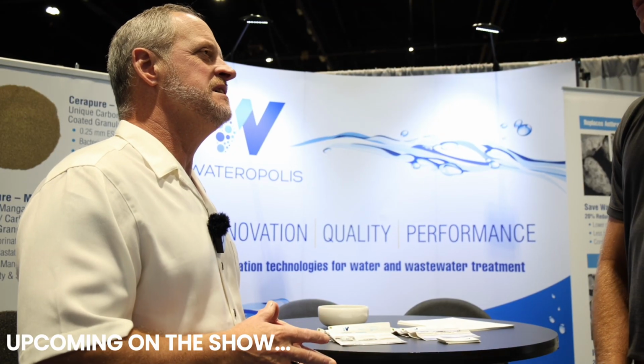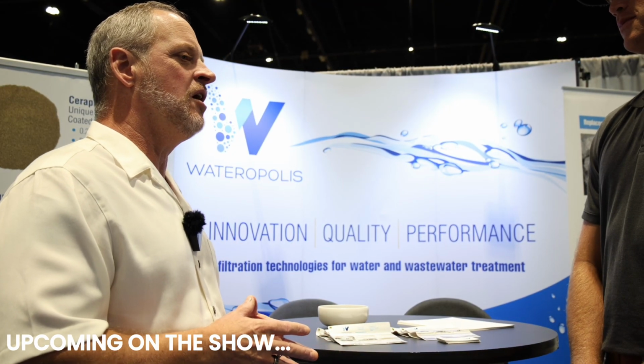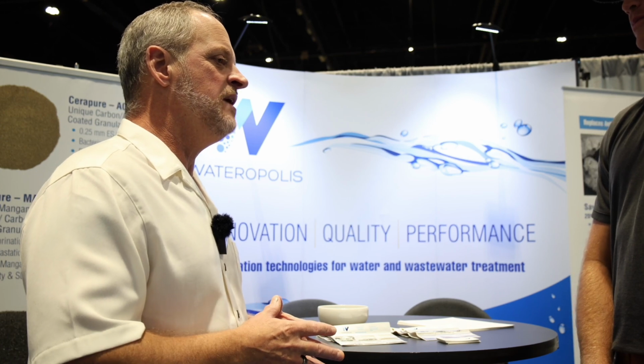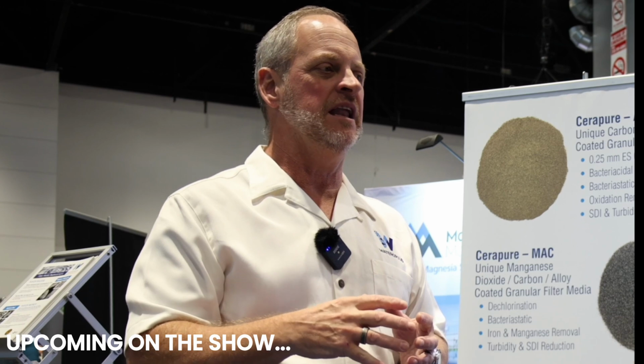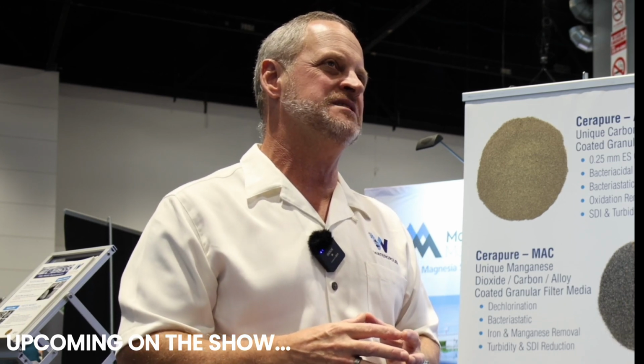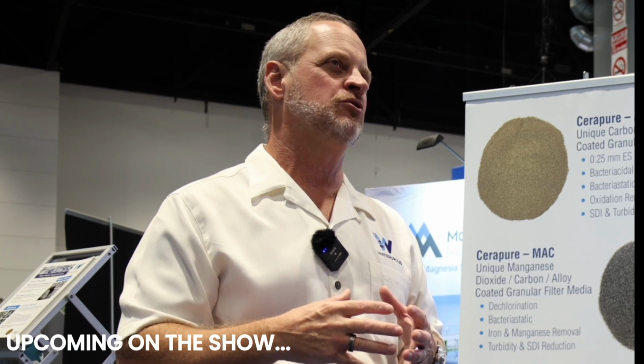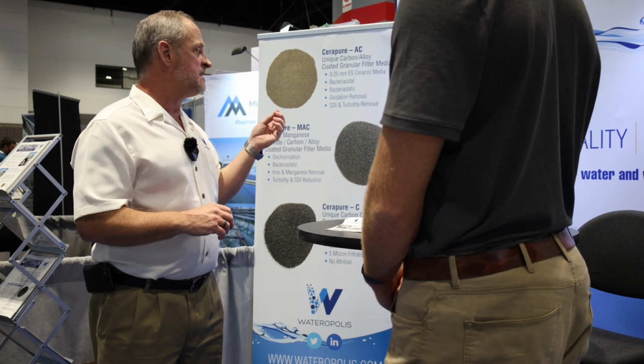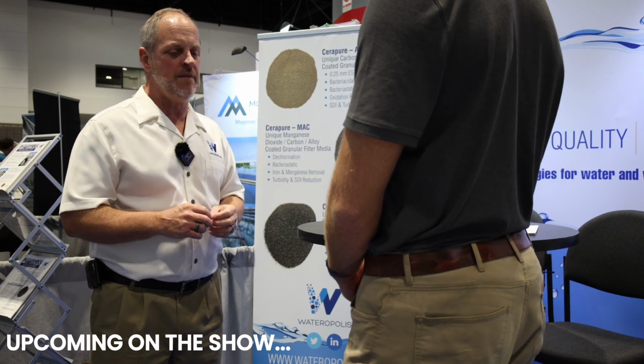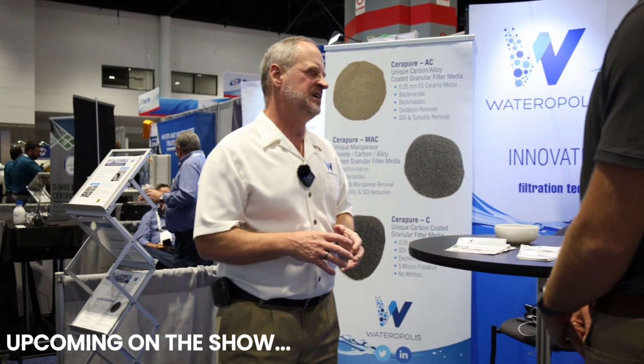Iron is generally easier to remove. You know, you can oxidize iron and then you have a number of choices. Most removals are a little less fussy about which crystal structure it ends up being. I guess the point is that manganese is a complicated mineral and a complicated thing to remove sometimes. If you use a manganese coated material, which we make, you can mitigate some of the potential for that pink